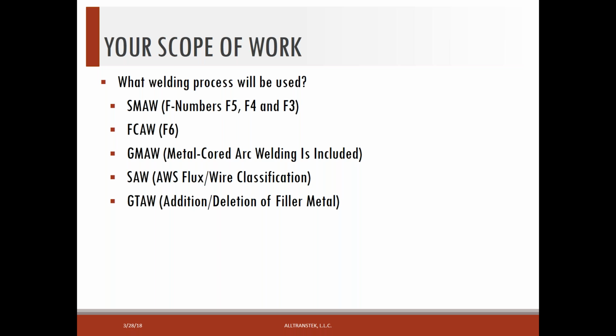And then one thing that some people have had problems with in gas tungsten arc welding is the addition or deletion of filler metal, which is an essential variable for qualification under that welding process. In other words, if you qualify with filler metal and you try to use this as a process without filler metal, then that has to be qualified separately, because that is an essential variable.